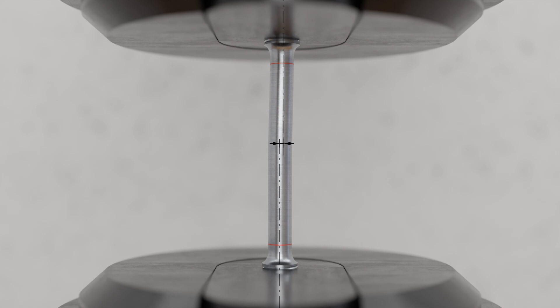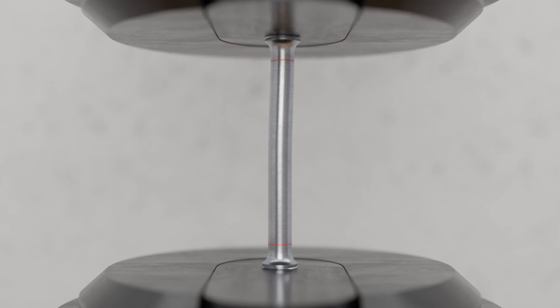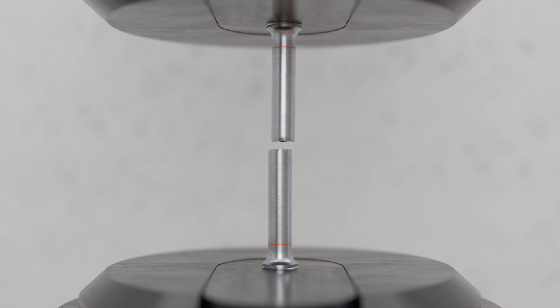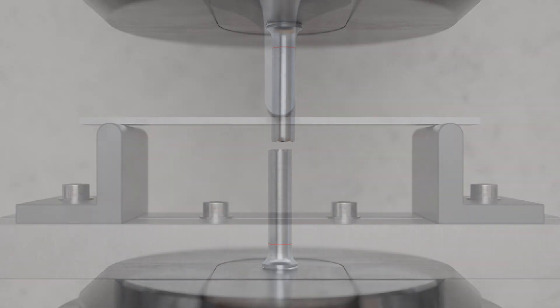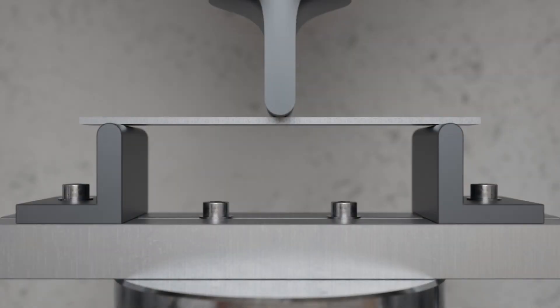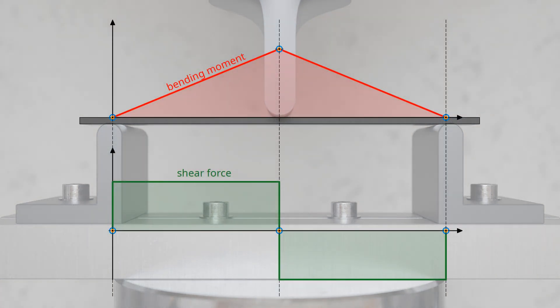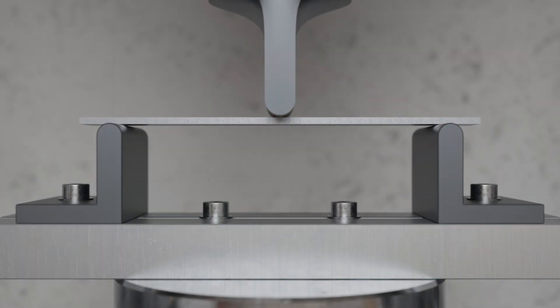In contrast to tough materials, a misalignment of brittle materials can almost not be compensated by deformation. Even when the specimen is slightly tilted, very high bending stresses occur, which cause the specimen to break prematurely due to the combined stress of tension and bending. The flexural test can therefore be more suitable than the tensile test for testing brittle materials, since the material is exposed to a pure bending load. However, this must be somewhat relativized, because the three-point bending test has the disadvantage that in addition to tensile and compressive forces, shear forces also act in the material. For this reason, the four-point flexural test was developed.